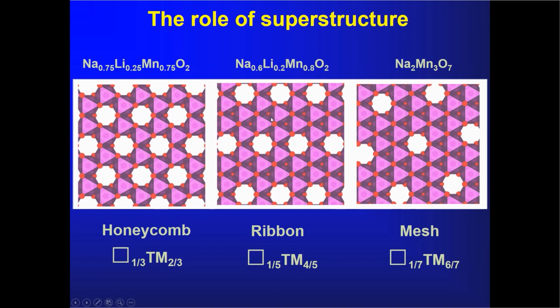So these are the transition metal ions in purple, and we've charged the cathode, removed lithium from these lithium sites in all cases. Now, as I showed you before, just 2 manganese displacements create the conditions for molecular oxygen to form here. In the case of the ribbon structure, you have to undergo rather more displacements of manganese before you can create a vacancy cluster that would allow or permit the formation of molecular oxygen.